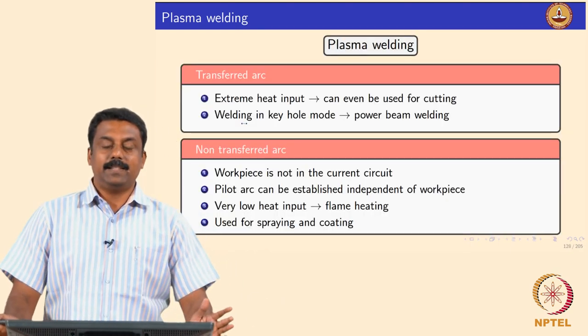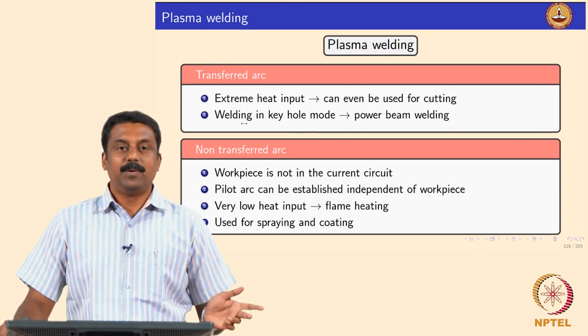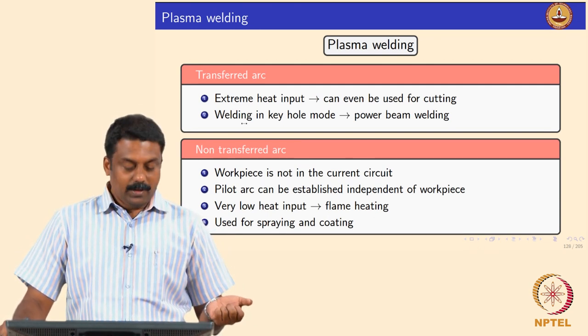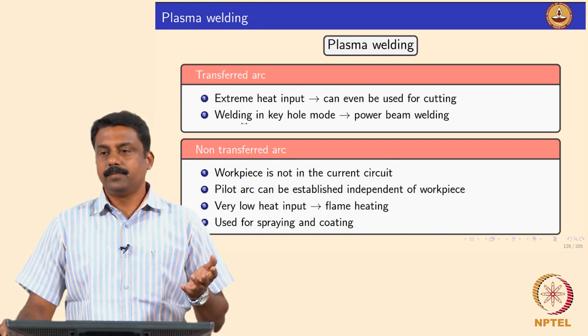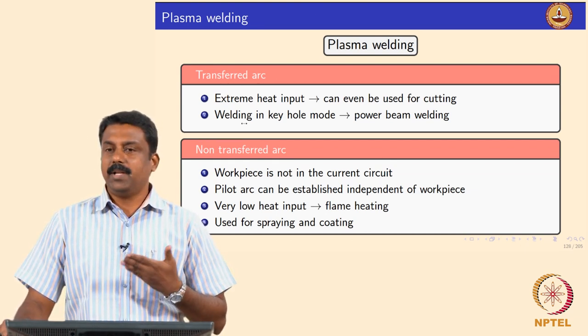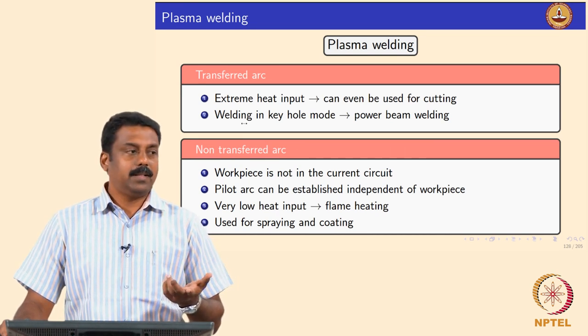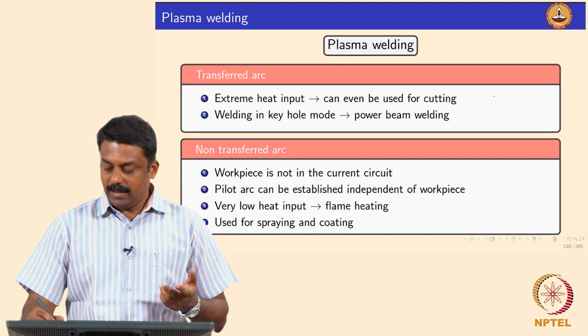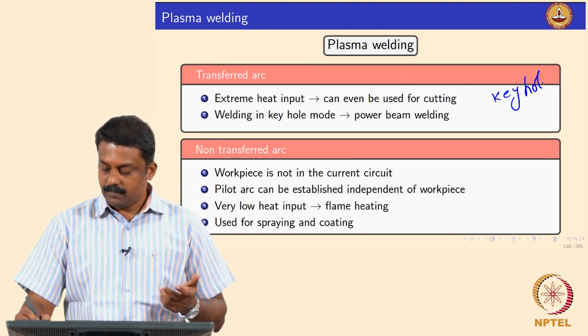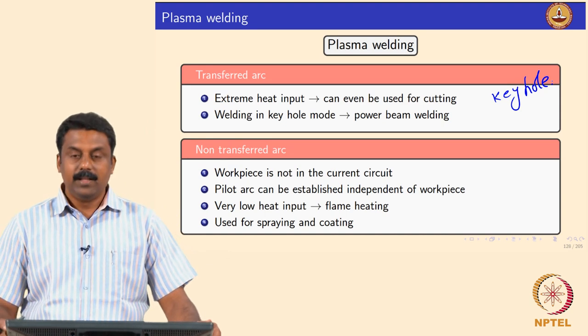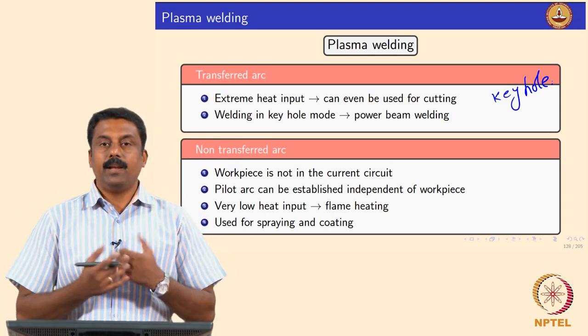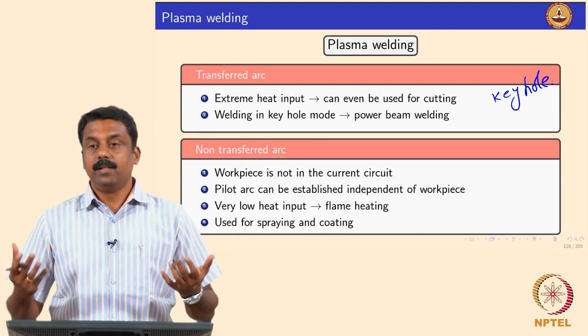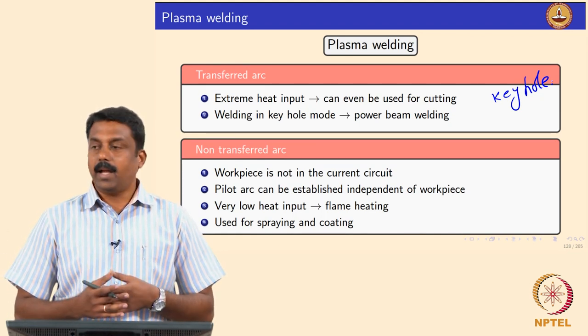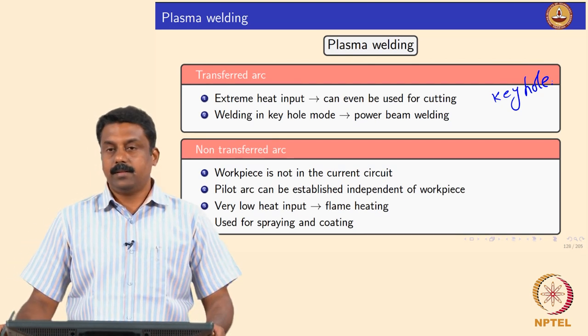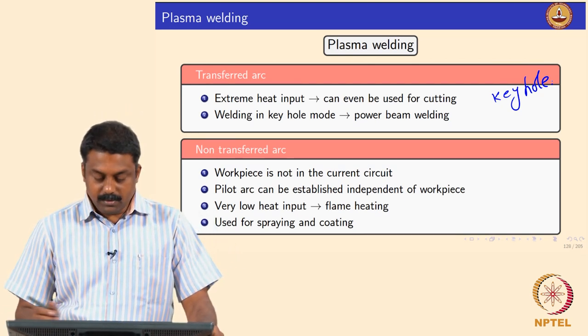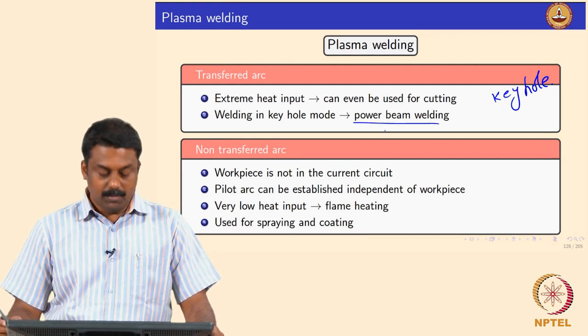So, what are the characteristics? As I said, we have two modes, transferred arc mode and non-transferred arc mode. In transferred arc mode, we can generate extremely high heat input. Because of the plasma jet formed by constricting the arc, you can have what is known as keyhole welding. What is keyhole welding? We will see in subsequent slides. If you have complete full penetration, we can achieve what is commonly achieved in laser welding. The power density of the beam can be even higher than some of the lasers we use. So, similar to that is what is known as power beam welding in keyhole mode.